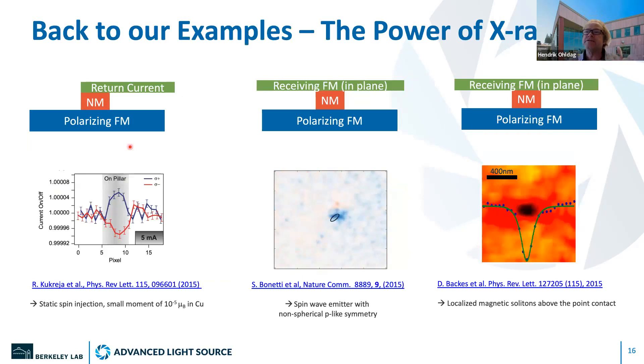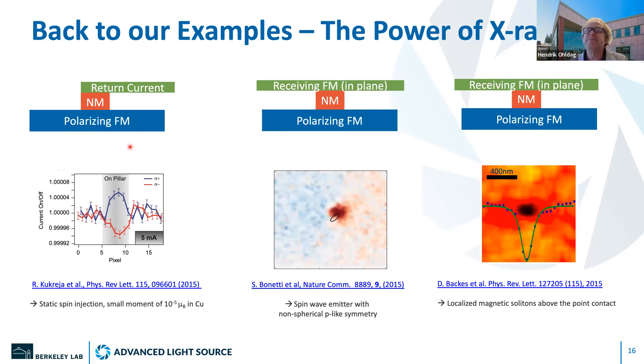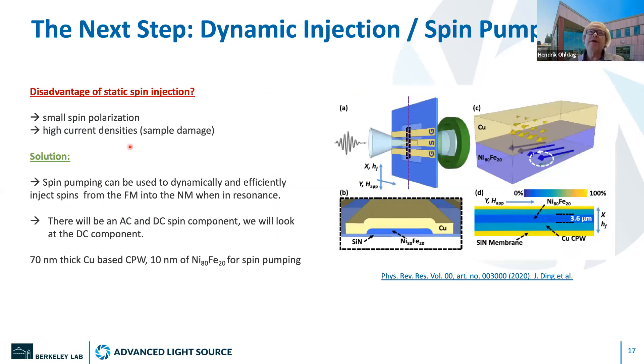What was happening is that we have dynamics driven not only by the external fields, but also by the dipolar fields. Because on the nanoscale, everything is very closely together — the cobalt-iron is essentially a big permanent magnet right next to the permalloy with a big field. That defines the energy landscape in the free layer, which is not homogeneous but heterogeneous, and that leads to this very directed emission of a spin wave. To summarize this part: these were the three problems we set out to solve almost 10 years ago. We were very lucky to find great collaborators, and these efforts culminated in a couple of papers a few years ago.